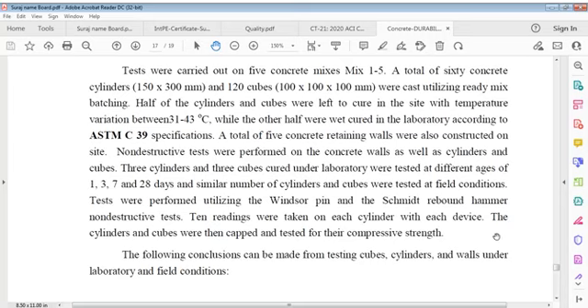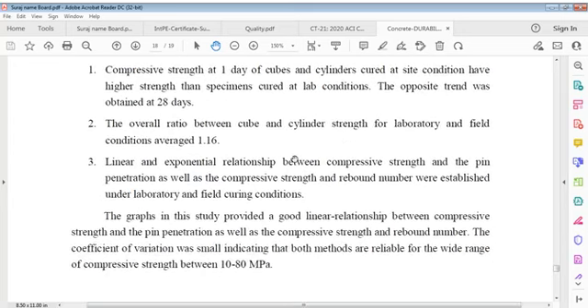The following conclusions can be made from testing cubes, cylinders and walls under laboratory and field conditions. Compressive strength at 1 day of cubes and cylinders cured at site condition is higher than that of specimens cured at lab conditions. The opposite trend was obtained at 28 days.